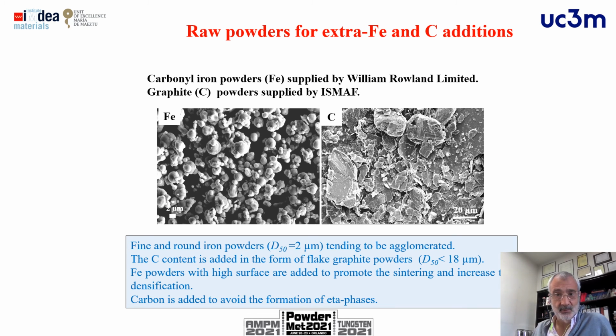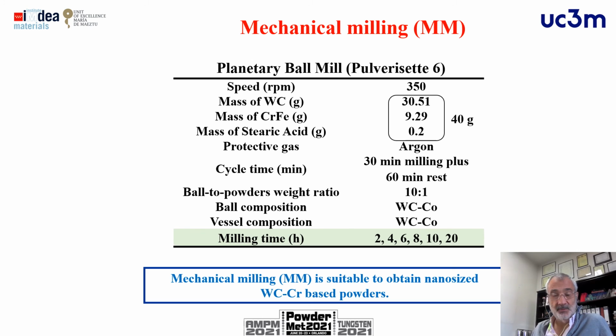As carbon and extra iron powders, the iron powder that we have used is carbonyl iron powder, supplied by William Rowland Limited. This powder is quite a fine powder, very small size, and this will contribute to increase the sintering behavior. The carbon is natural carbon, added in principle to avoid the formation of eta phases, and this carbon is also a conventional carbon used in conventional powder metallurgy. So the first step is to integrate the carbon or the iron, or also the iron chromium binder, with the tungsten carbide powders, and we did it by mechanical milling.